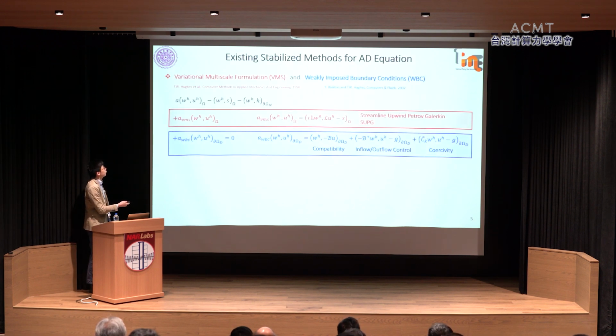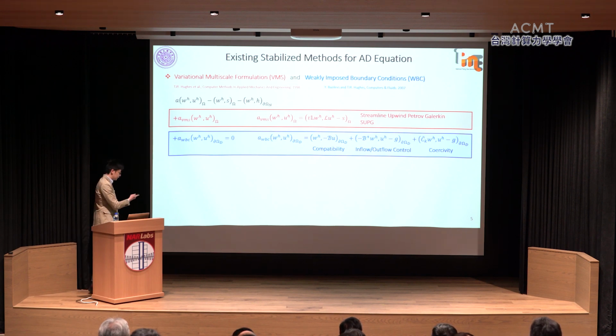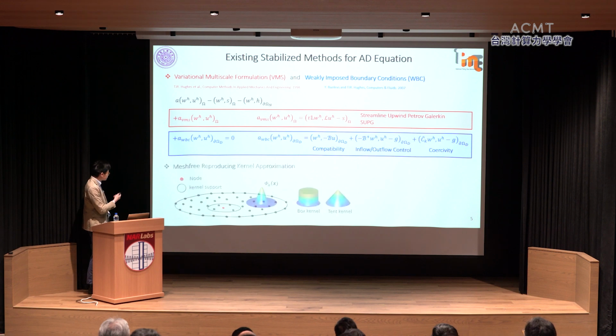So there's a well-known method by the big name Tom Hughes, the variational multiscale method. You can use that to stabilize the results, and for boundary conditions, you can use weakly imposed boundary conditions by Yuri Bazilevs and Tom Hughes again to solve the problem. The idea is they introduce streamline upwinding, the well-known SUPG formulation, and also Nitsche-like formulation to impose compatibility, regularization on the inflow and outflow, and also introduce additional coercivity to enhance the solution stability.